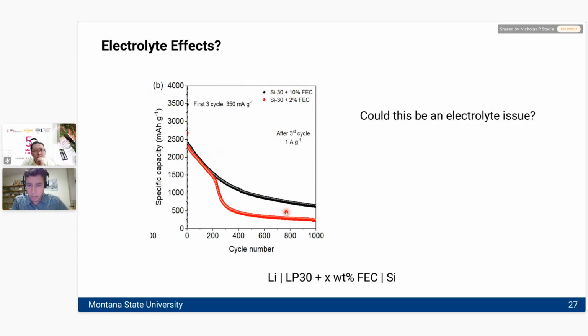On this slide, I'm showing you the same exact electrode, charged and discharged in the presence of an additive, an electrolyte additive called FEC, fluoroethylene carbonate. It was only present in 2% ratio in the original electrolyte here in red. When we increased that to 10%, for example, we managed to solve this problem completely. So electrolyte engineering has a very important role in any kind of lithium-ion battery research.